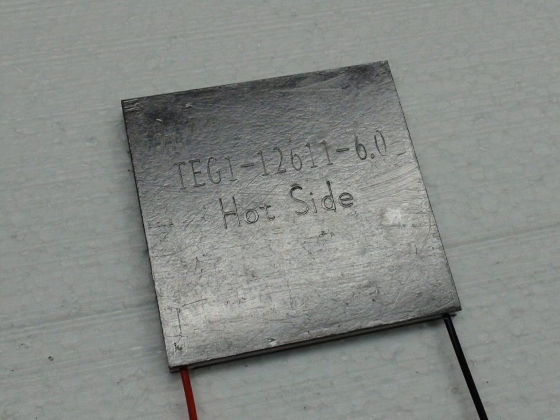Besides improving the figure of merit, there is increasing focus to develop new materials by increasing the electrical power output, decreasing cost, and developing environmentally friendly materials. For example, when the fuel cost is low or almost free, such as in waste heat recovery, then the cost per watt is only determined by the power per unit area and the operating period. As a result, it has initiated a search for materials with high power output rather than conversion efficiency. For example, the rare earth compound YbAl3 has a low figure of merit, but it has a power output of at least double that of any other material, and can operate over the temperature range of a waste heat source.